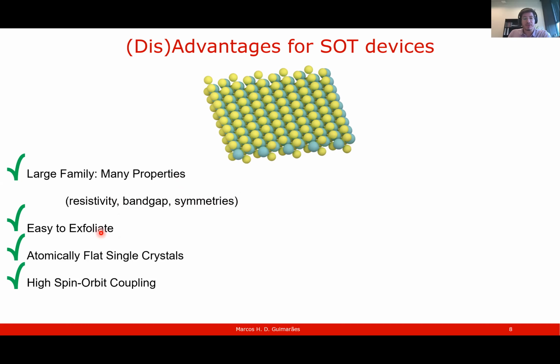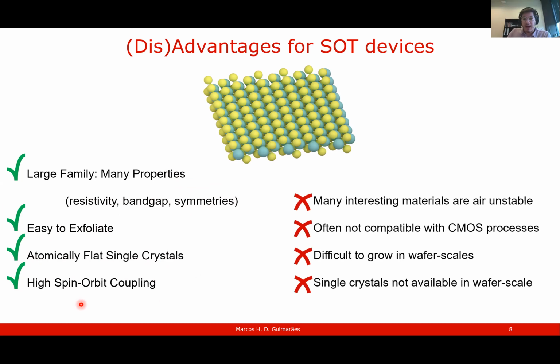And they're easy to exfoliate and get atomically flat single crystals, which is important to the study of the symmetries and the impact of the symmetries on the spin orbit torques. And they can give you a large degree of values for the spin orbit coupling. However, there are a few disadvantages, and those are that many of the interesting materials are air unstable, so we need to work with care.